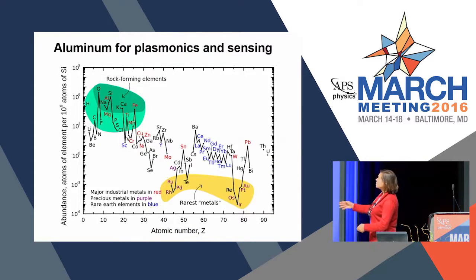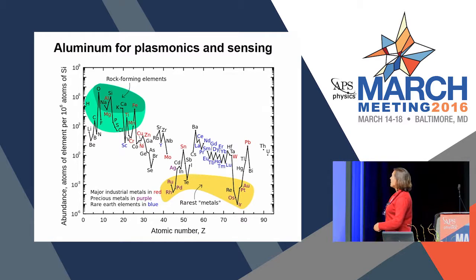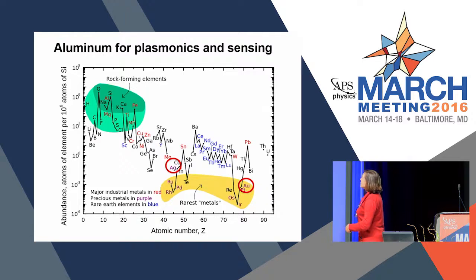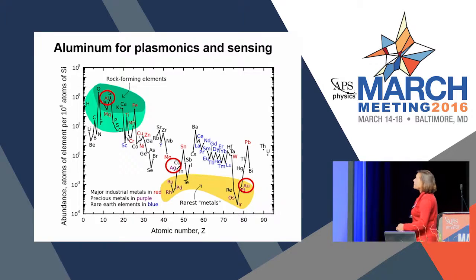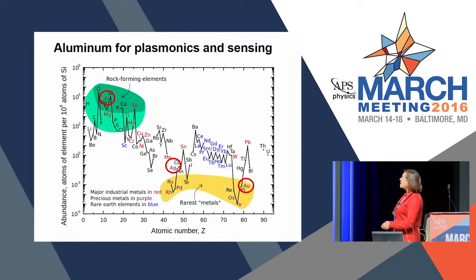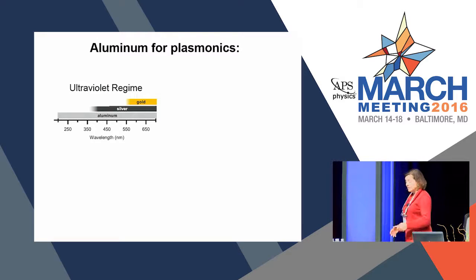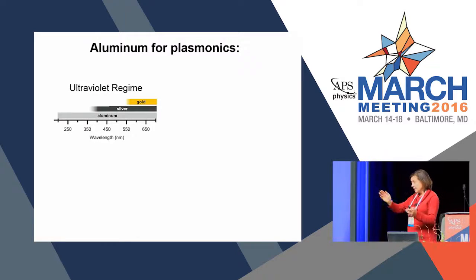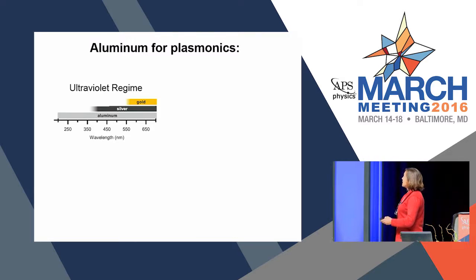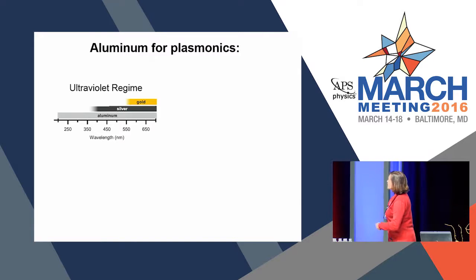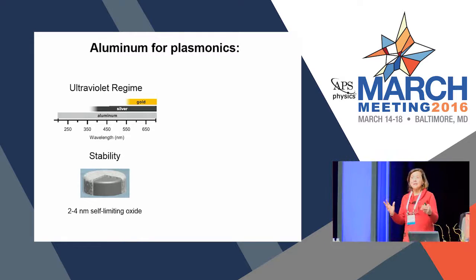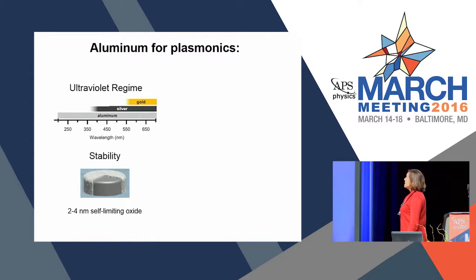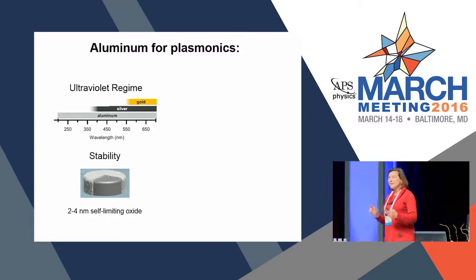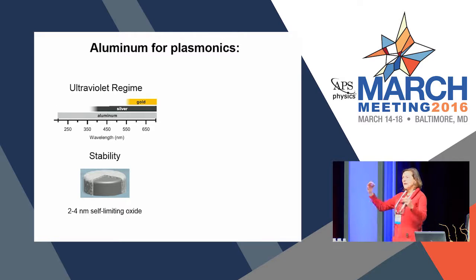And so if we look at a chart of the abundance of metals at the Earth's surface, we see that gold and silver are down in the more rare metals, but aluminum is in fact the most abundant metal at the Earth's surface. And so we can begin to look at the properties of aluminum. Aluminum has a plasmon resonance that one can tune across the visible and the ultraviolet region of the spectrum, not unlike silver. But unlike silver, it's actually remarkably stable. Silver oxidizes very readily. So does aluminum, of course. It's highly reactive. But it forms an oxide that then arrests further oxidation. So it has a very stable oxide layer.